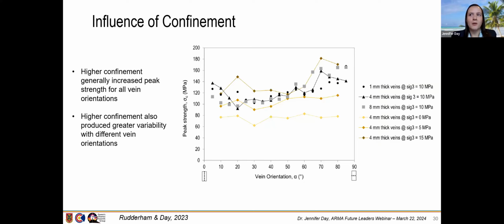Looking at the influence of confinement, when you think about triaxial tests going from 0 MPa confinement for UCS tests through to 5, 10, and 15 MPa, generally in this experiment, the higher confinement increased peak strength for all vein orientations, as you would expect, but it also produced greater variability with different vein orientations. So the amount of increase in peak strength was much higher at vein orientations of less than 30 degrees and more than 60 degrees.